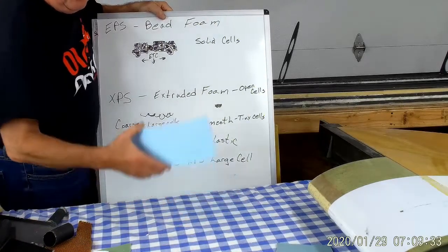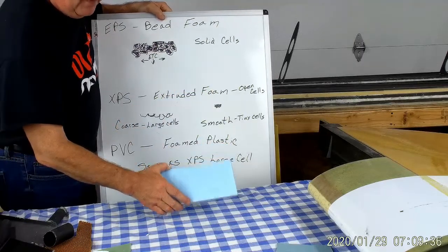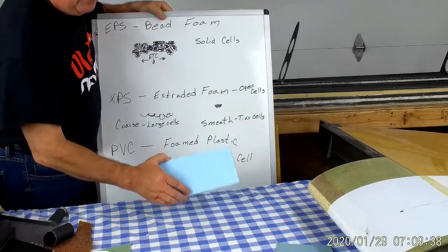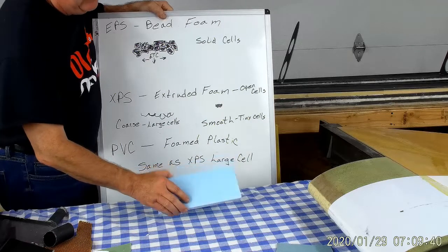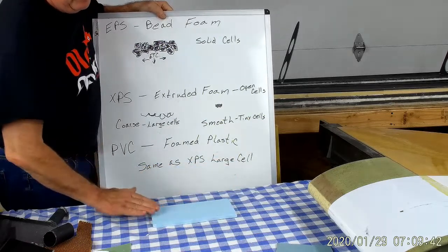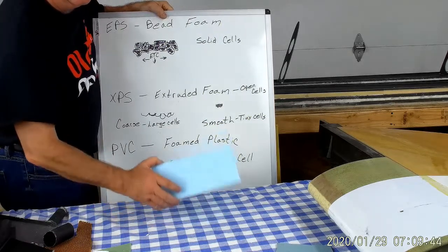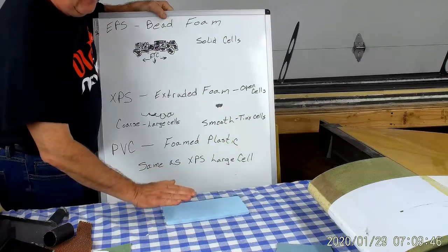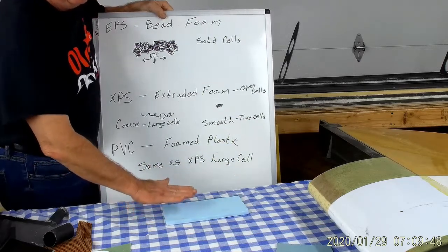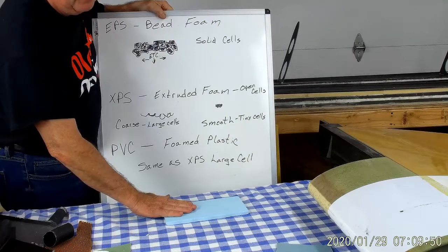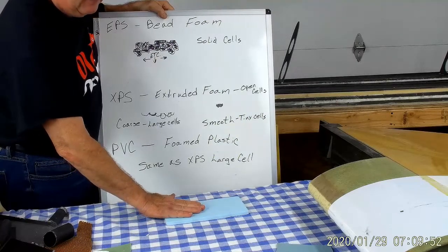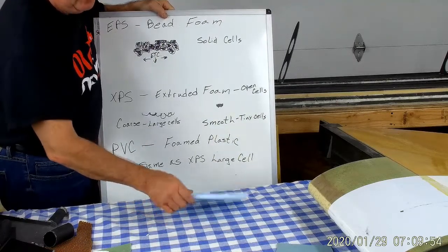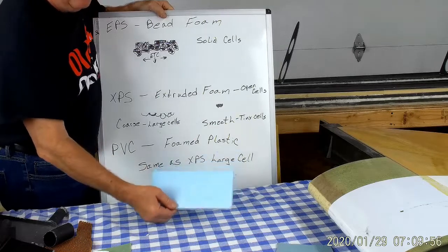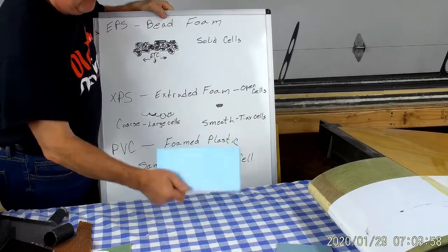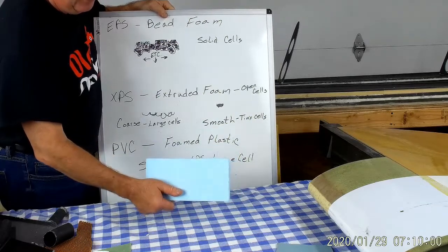And with this type of foam, you don't add a lot of weight by the foam sucking up extra resin, and you don't have to worry about filling it with microballoon filler or anything like that. Its drawback is its low compressive strength does not allow it to be vacuum bagged. If you vacuum bag this stuff, the vacuum is high enough to begin to compress the foam, and then your final part comes out the wrong size and your foam is all squished, and it's a bad plan.